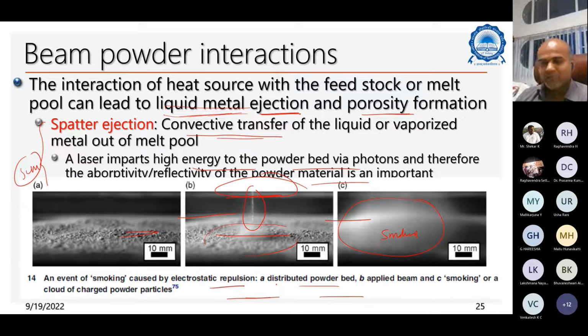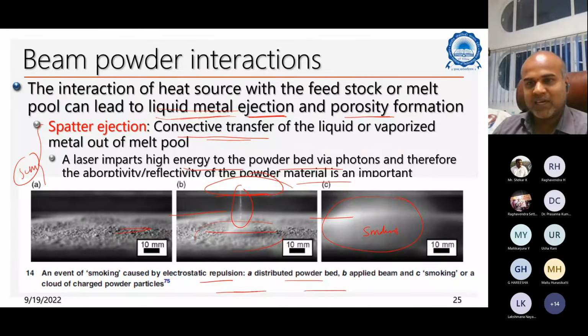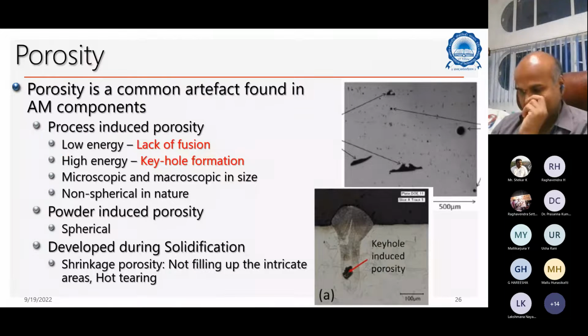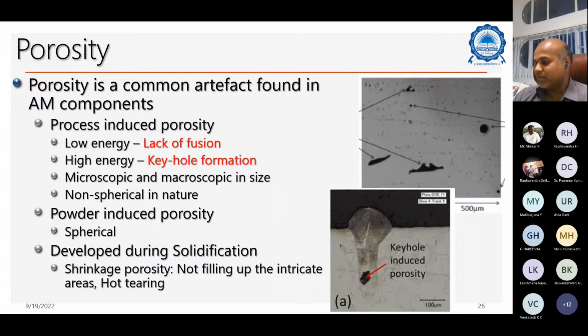So these are some of the beam powder interactions which also lead to certain kinds of porosity. Coming to here, if you look at any additively manufactured product, you make it and then look at the microstructure here, you see small pores, and you see large pores.